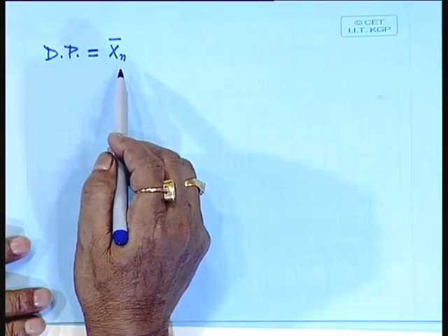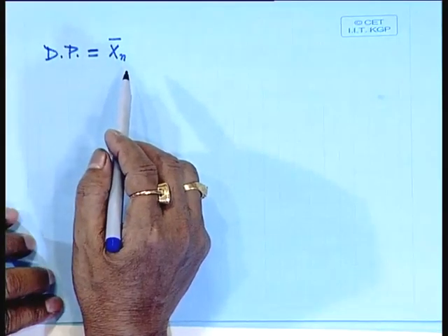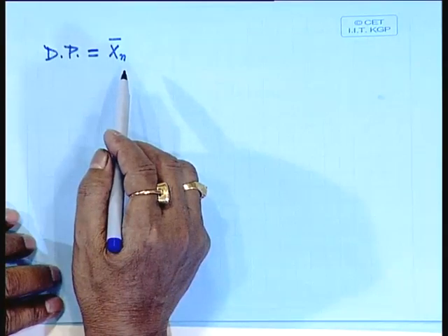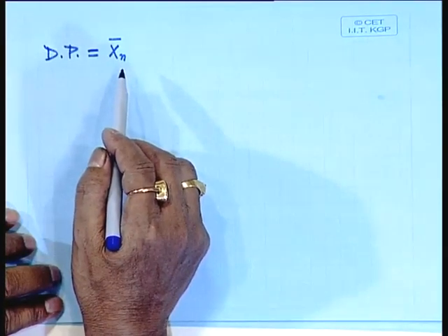The concept of average molecular weight in polymers comes from the situation I already explained in previous classes: the polymer molecules in a sample of polymer do not contain the same molecular weight. There is a distribution of molecular size. Here lies a difference between discrete small molecular compounds and polymeric compounds.